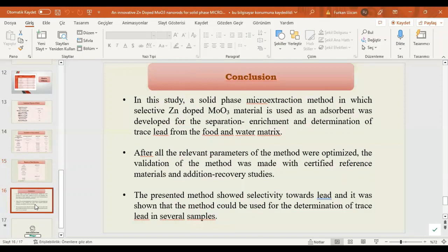As a conclusion, in this study, a solid phase microextraction method in which selective zinc doped molybdenum oxide material is used as an adsorbent was developed for the separation, enrichment, and determination of trace lead from the food and water matrices. After all parameters of the method were optimized, the validation of the method was made with certified reference materials and addition recovery studies. The presented method showed selectivity towards lead, and it was shown that the method could be used for determination of trace lead in several water and food samples.